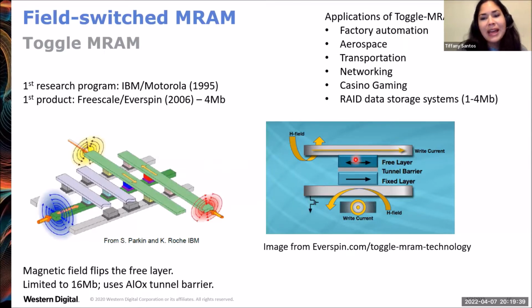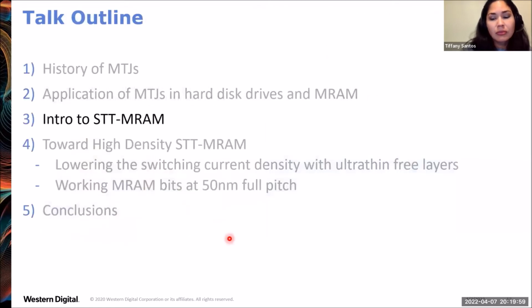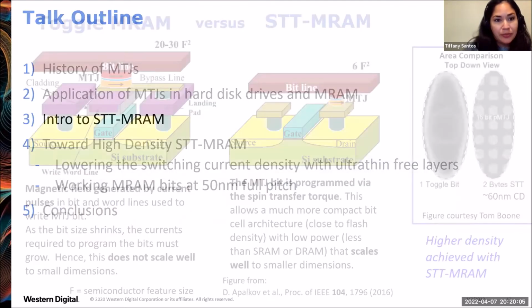And you flip the magnetization of the free layer by a local magnetic field. The magnetic field comes by passing a current through the word lines and bit lines high enough to generate the field to switch the magnetization of the free layer. Okay. And these use aluminum oxide tunnel barriers. Okay, so at this point on, I will now describe spin transfer torque MRAM.